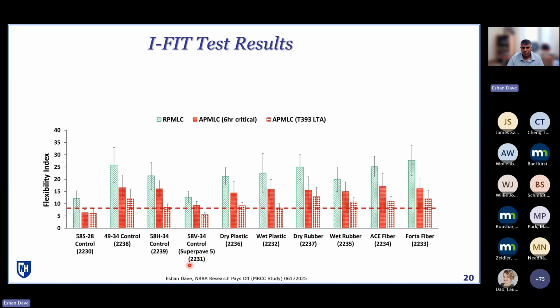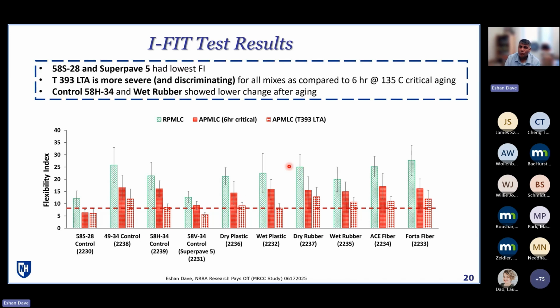Once again, the two mixes that had the lowest properties are the control mixture and the Super Pave 5. All the other ones, I think statistically, at least in unaged condition, are very comparable. And also in aged condition, there wasn't too much of a difference. One thing that we did see was that the amount of drop from unaged to aged was a little bit lower on the 58H minus 34 and wet rubber. They did not have as much of a drop. The other ones continued on a similar trajectory as they went from first to second aging condition, then second to third.